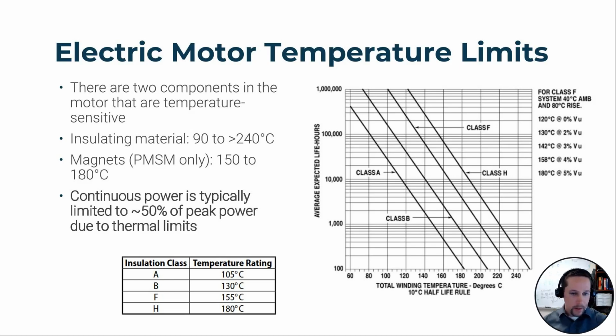And you can see here on this graph that some of the most important considerations are looking at the expected life hours of the motor and how the total winding temperature determines how long the motor will last. And as an example of the types of problems that engineers face, continuous power is typically limited to about 50% of peak power, and that's due to thermal limits. So designing a better thermal management system or a better motor with different materials can really increase the amount of power that you can get out of them.